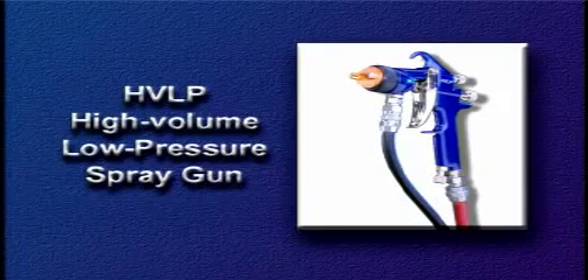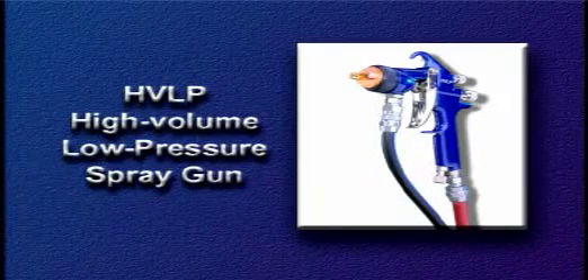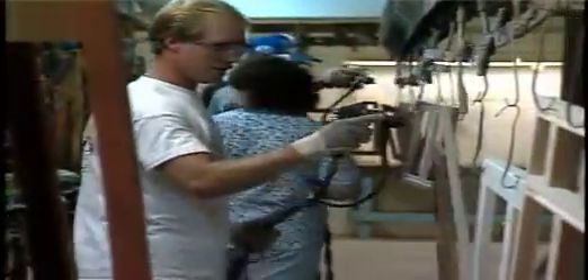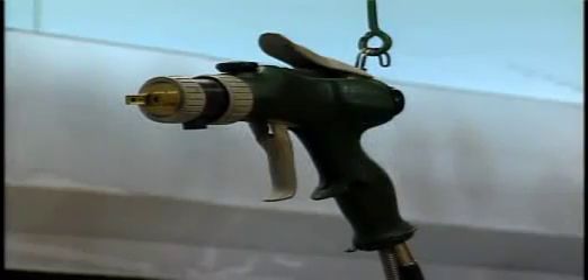Another type of spray application equipment is the high-volume, low-pressure spray gun. With this system, a turbine or compressor is used to generate a high volume of warm, dry atomizing air that is delivered to the spray gun at pressures of 4 to 6 psi. This low-pressure air gives greater control over the spray, with less of the overspray and fogging that accompanies the blasting effect common with conventional high-pressure systems. Transfer efficiencies of 60 to 70% have been reported for this application method.